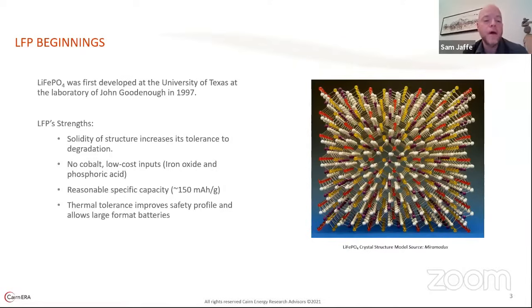It has a reasonable practical specific capacity of around 150 milliamp hours per gram, which translates into a low energy density material, 120 to maybe 150 watt hours per kilogram in its current state, but it's good enough. And of course, it has much better resistance to thermal runaway, which has a lot of implications. It is inherently a safer battery chemistry than others. But because of that thermal tolerance band going wider, you can actually make a larger format cell more safely. And that has a lot of implications too.